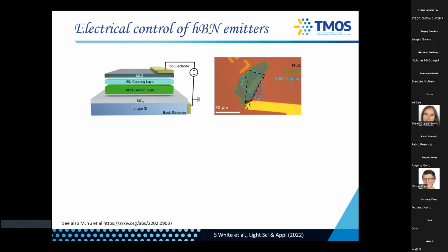And one follow-up question on the structure. I don't know whether this is the case with hBN, but have you considered putting the hBN capping layer between the SiO2 and the emitter layer? Because often there are charge traps in SiO2 or just spatial inhomogeneity. Yes, that we did. We did capping under, over, played with the capping layers. That had no effect on the results. Oh, that's good. So electrostatically speaking, this is not a good device. It's just fit for purpose for the emitter manipulation, basically. But electrostatically, it's definitely not optimized.